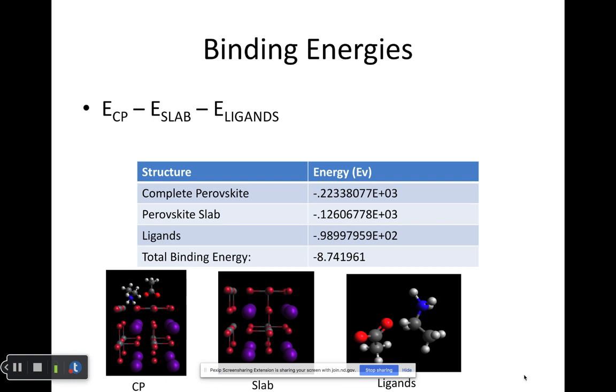So intuitively you expect that the charged species should interact strongly. But from his images, it appears that he computed the ligands in a single box, so you could have charge interaction between the ligands. It's an interplay of several effects. Just think only about the bottom left, remove only the carboxylic ligand and compute the binding energy according to your standard procedures.